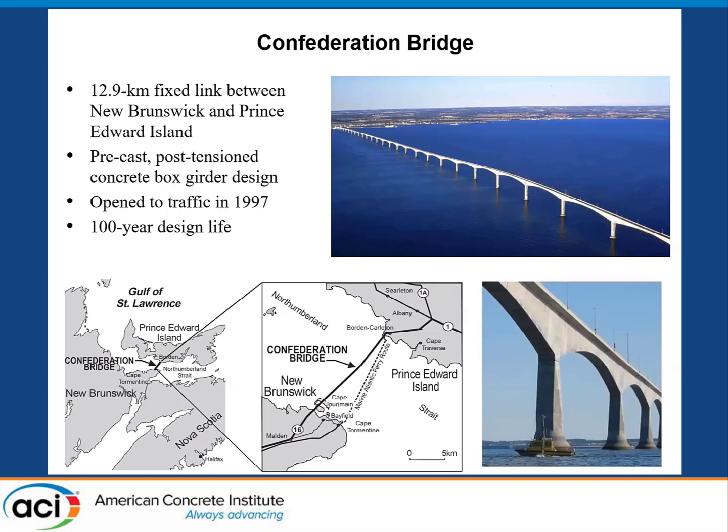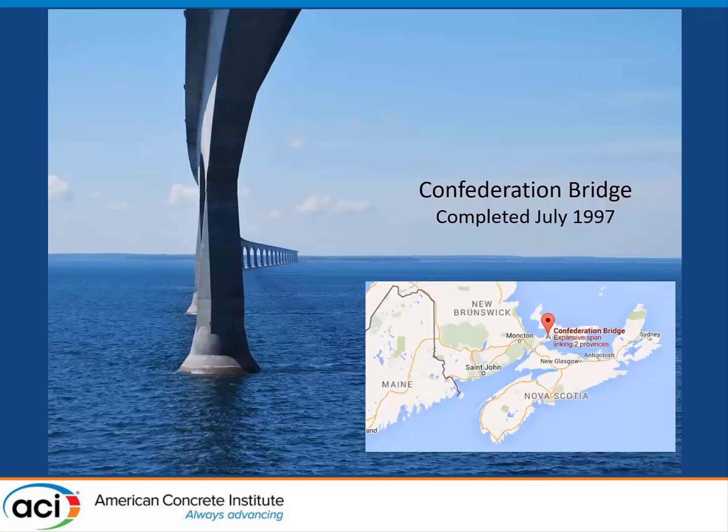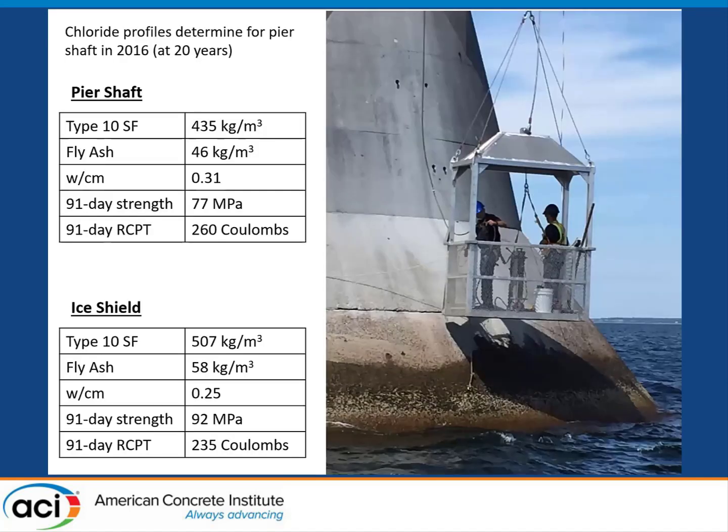It was open to traffic in '97, and a beautiful looking structure. We profiled it at an age of 20 years, and we took profiles both from the piers at different elevations on the piers and also from the ice shields. You can see the different mix designs there. There's some similarity. The ice shields, though, because of abrasion resistance, they were targeting 100 MPa concrete, but otherwise fairly